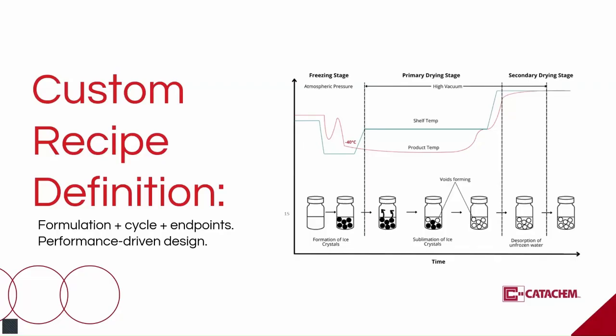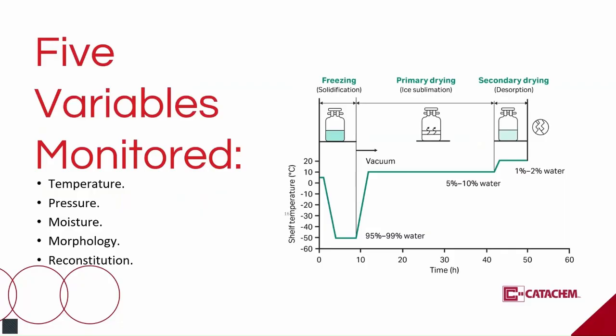Catachem's value here is not that we run a cycle. It is that we can develop the right cycle quickly, prove it with data, scale this to commercial volume, and then lock the process into controlled manufacturing. In practice, we track 5 variables as the backbone of process control: product temperature, chamber pressure stability, residual moisture, cake morphology, and reconstitution performance. These are not academic. They are the variables that predict whether your stability data will hold up, whether your end users will get consistent results, and whether your lots will remain comparable across time and geography.